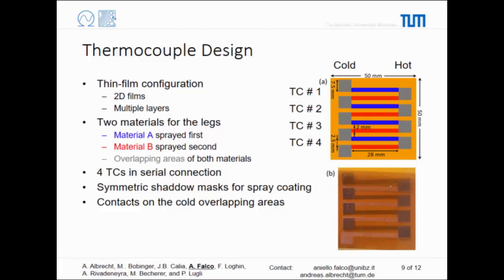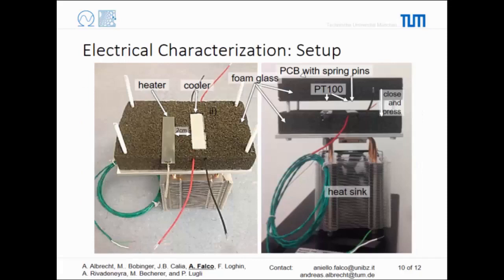For the characterization, we developed our own setup, which is composed of a ceramic heater and a thermoelectric cooler, and this way we are able to keep the temperature gradient. And there is a heat sink, of course, because we wanted really to achieve the 300 degrees in thermal gradient. In the end, we did not do it because one of the materials degenerates with temperature, especially PEDOT PSS loses all its properties above 150 degrees.